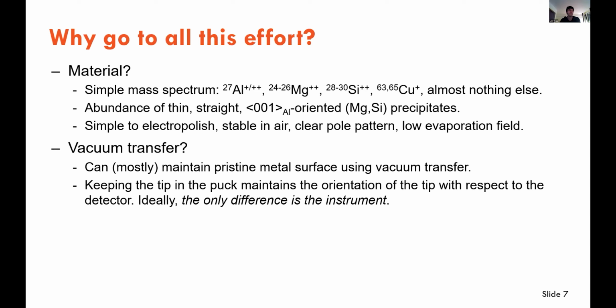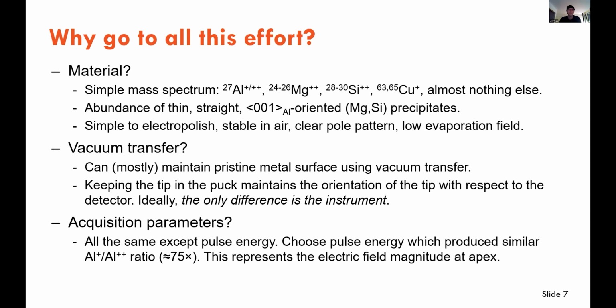So whatever this exit surface was from the 4000 should be the starting surface in the 6000. Another advantage is that by not taking the tip out of a puck, we keep the orientation of the tip the same with respect to the detector to really try and minimize the differences. The only difference should be the instrument, in theory. And then all acquisition parameters were essentially default except laser pulse energy. And as I'll get to, we chose this based on the single plus, double plus charge state ratios.